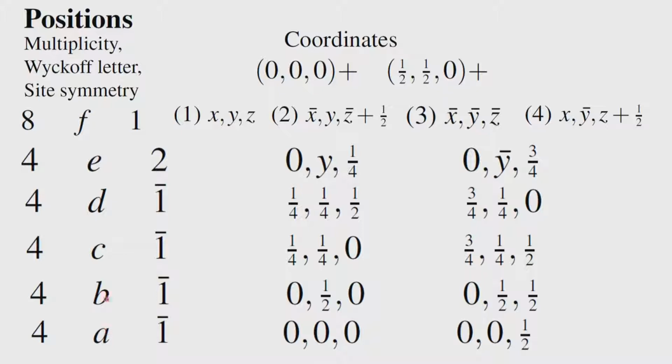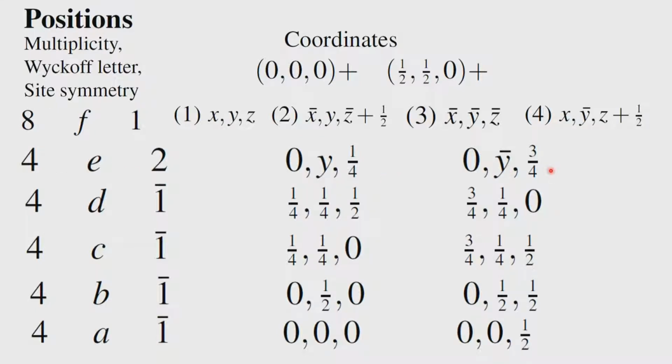So, it is going up there, and we see that 4e is a position where you can have a twofold symmetry. So, objects which have twofold symmetry preferably sit there rather than in any one of these positions, because these positions insist on having the center of symmetry. So, if the molecule has a center of symmetry, it prefers to go into these 4 positions, and if the molecule has a twofold symmetry, it prefers to go to that particular system.